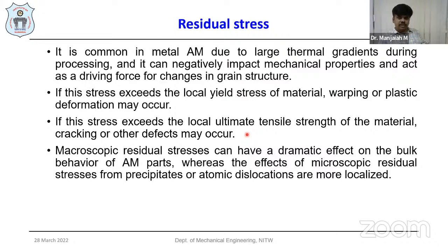Another is the residual stresses, which are the most common in all metallurgy manufacturing components, due to large thermal gradients during the processing. They can negatively impact the mechanical properties and act as a driving force for changes in the grain structures. If these stresses exceed the local yield stress of the materials, warping may take place or plastic deformation may also occur in the components. If these residual stresses exceed the local ultimate tensile strength of the materials, then cracking or other kinds of defects may occur in the components.